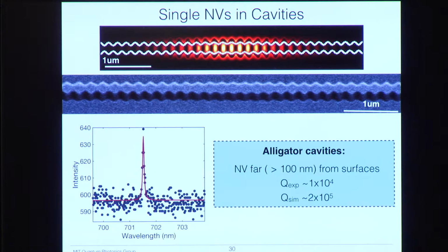So that inspired us to create what we call alligator cavities. Instead of creating this periodic modulation of the refractive index with holes, we create it with this sinusoidal modulation on the outside. So that creates the band gap out here. And then we create a defect in the center by changing the depth of the modulation linearly over 5 periods. And so that concentrates this mode at the center here. So this is an SEM of such a cavity.